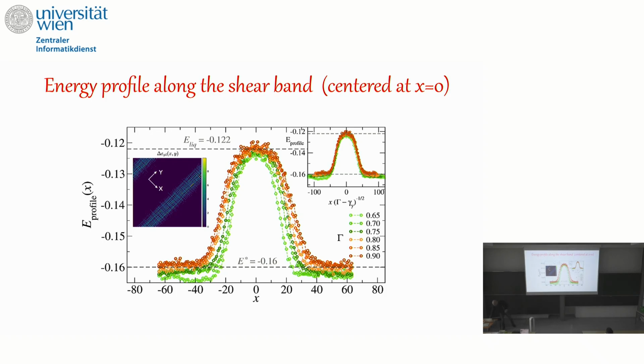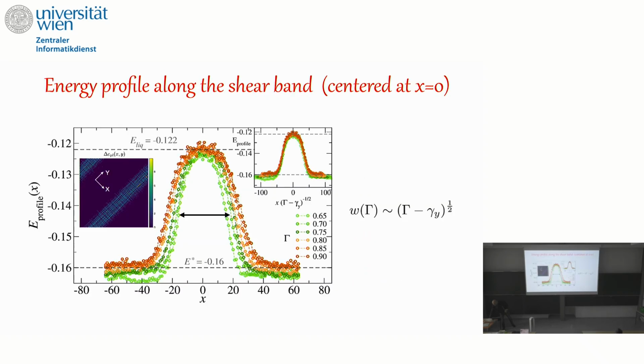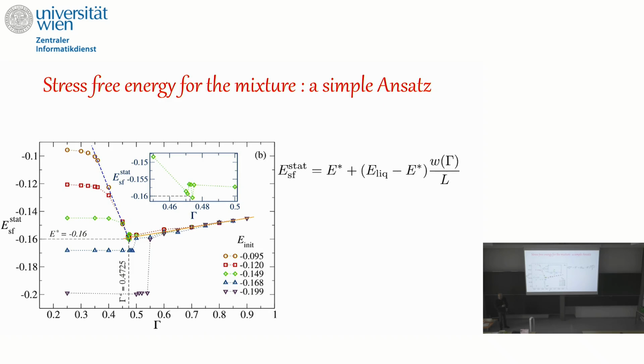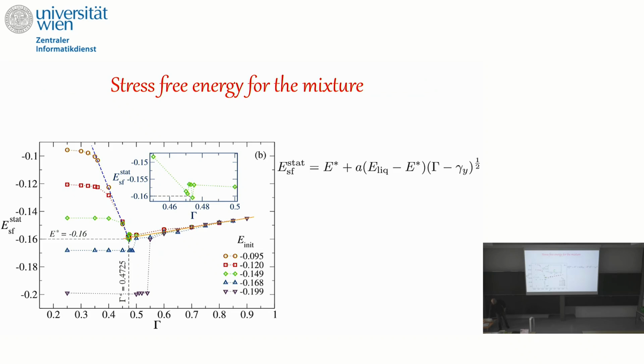And now if you rescale everything correctly, you get a nice collapse when you assume that the shear band has this form. So at gamma star, at the transition, the shear band is already finite. And so this is why we think the transition is of the first order, because you have a jump and it's not continuous. Here you have a small jump, and you can describe the energy. The yellow line is given by this analytical formula, which depends on only one parameter A, which is here, and we tested it.